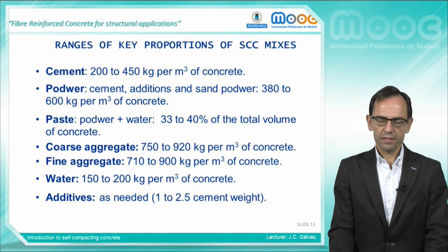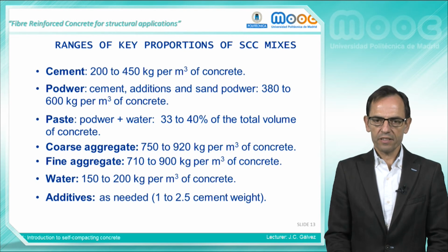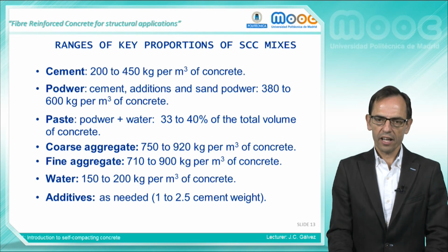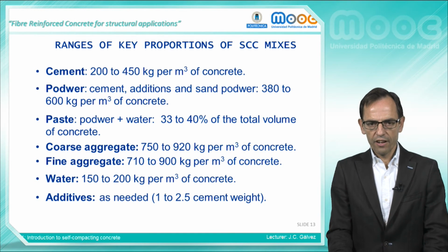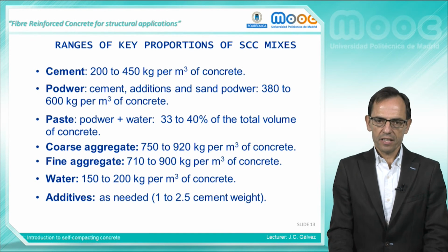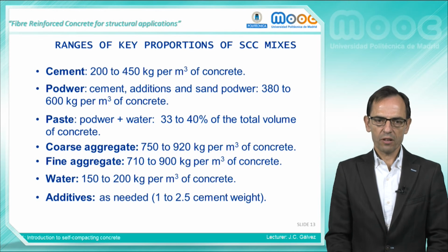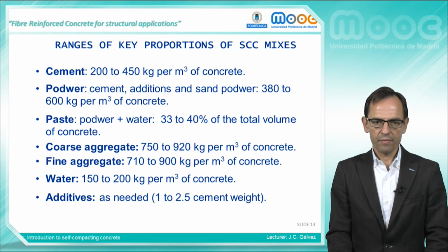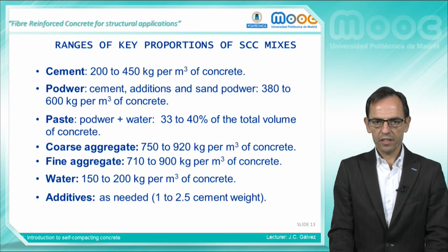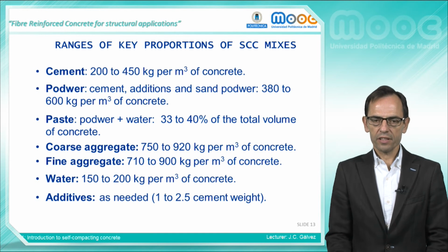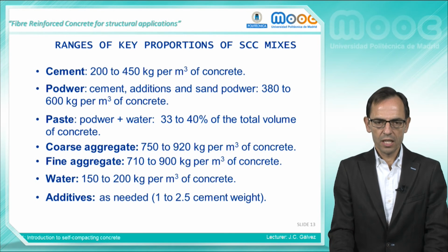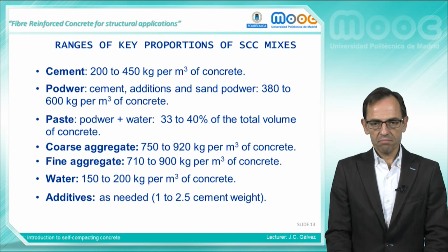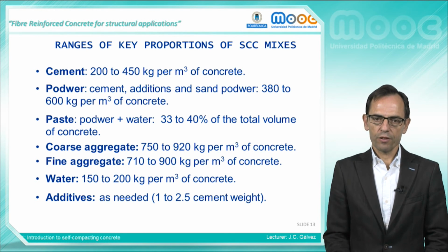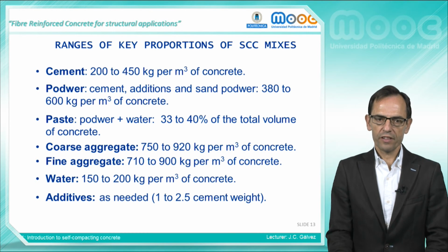Coarse aggregate, 750 to 920 kg per cubic meter of concrete. Fine aggregates, 710 to 900 kg per cubic meter of concrete. Water, 150 to 200 kg per cubic meter of concrete. And additives as needed, with typical values ranging from 1 to 2.5% of cement weight.